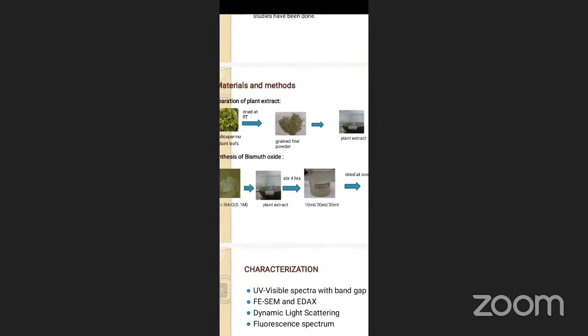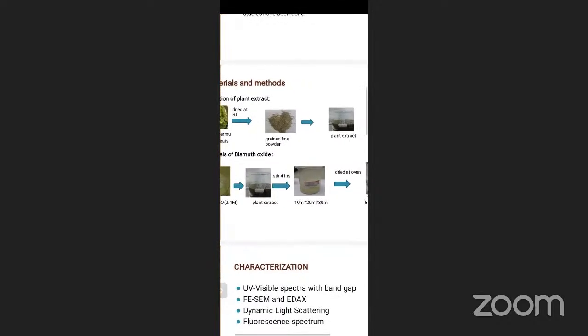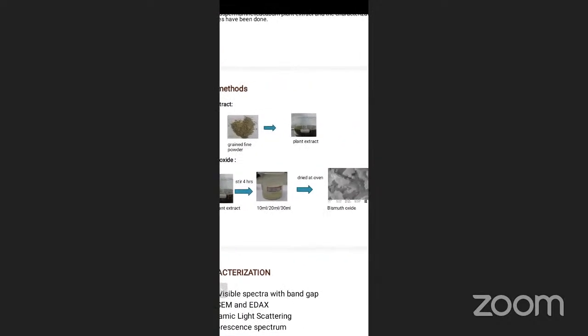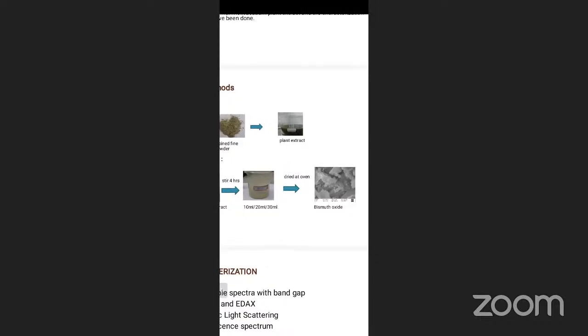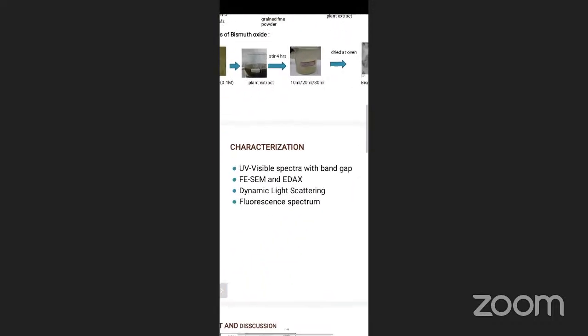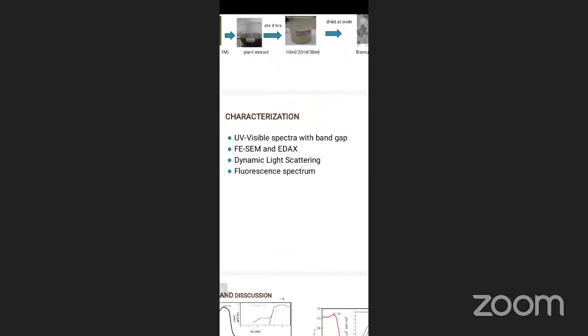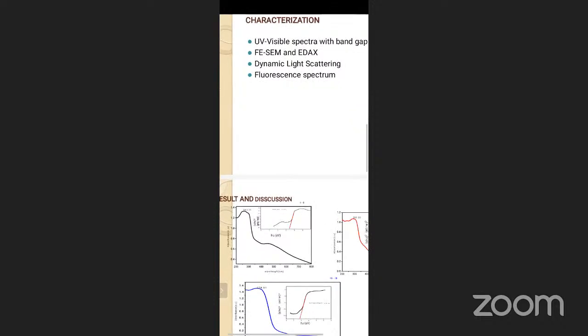For the three different solutions we made like this, after adding the plant extract, it was stirred for 4 hours, then centrifuged to get the precipitate, which was dried in an oven at 60 degrees Celsius, and then we get the bismuth oxide. For characterization, we did UV visible spectrum with band gap, FESEM images, EDAX, dynamic light scattering and the fluorescence spectrum.